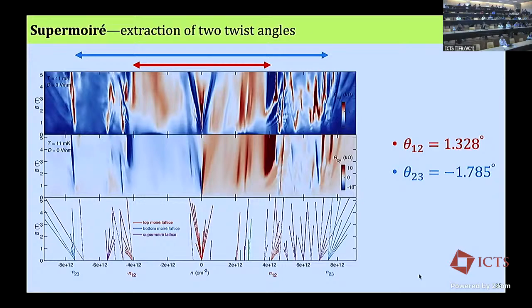Other question, this entire system is so rich. Are there vortices in these things? I would like to believe that. That's why we are parsing all these things. What is the Ginzburg-Landau? Pablo did a lot of this analysis. The coherence length is of the order of 30 or 40 nanometers, less than 50, if I remember correctly. The penetration depth, I think infinite. And what are your device sizes? They're like 50, 60 micron. So shouldn't things depend upon where the vortex nucleates?